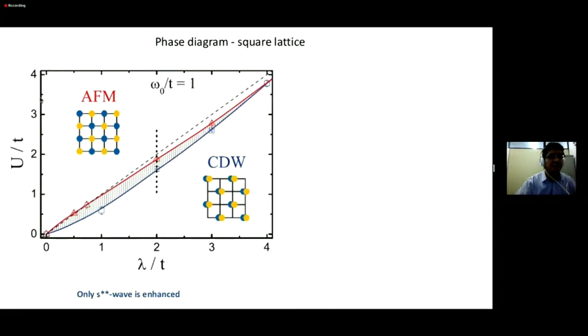So we could provide, for instance, a phase diagram for this kind of model. Here in our phase diagram, we see that if you have an electron-electron interaction much larger than the electron-phonon one, you have an antiferromagnetic phase, which is expected since we have stronger spin-spin correlations. If you go to a place where we have larger electron-phonon interaction than electron-electron, you have the formation of CDW. But at the boundaries of these two phases, which is quite interesting, we have the formation of a region that is not CDW, not antiferromagnetic.